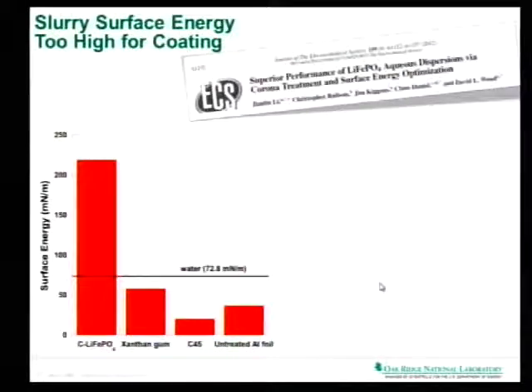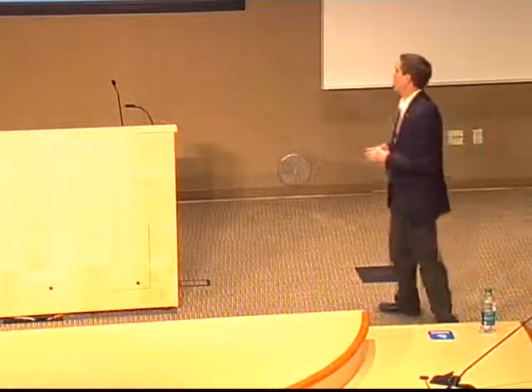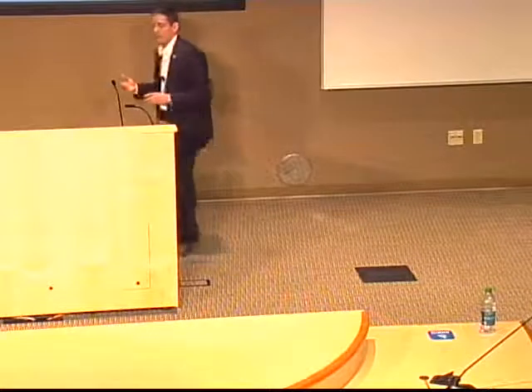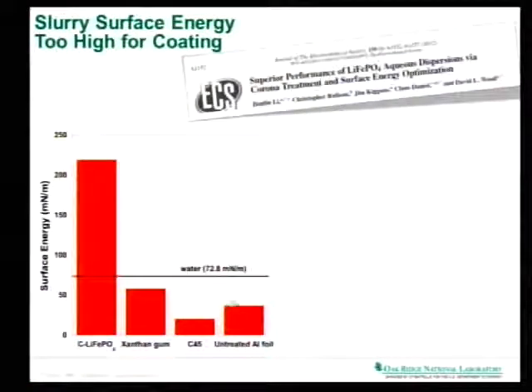So now the next big thing is, we all know that metal surfaces don't like water very much. On aluminum foil, for example, you have a very, very hard time making a water-based slurry that really wets the surface nicely. You need to wet the surface very nicely in order to have very good adhesion on your electrode, which really determines the long-term performance of the material. If we measure the surface energy of the untreated aluminum foil, it's much lower than the surface tension of water. That essentially results in water not wanting to spread out, but forming droplets and de-wetting from the surface.